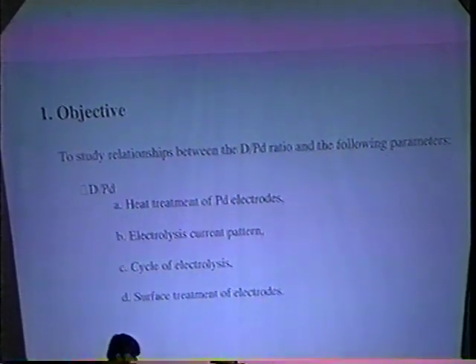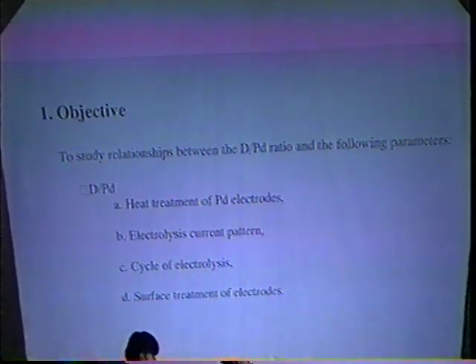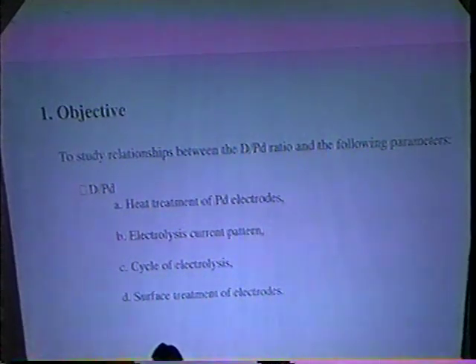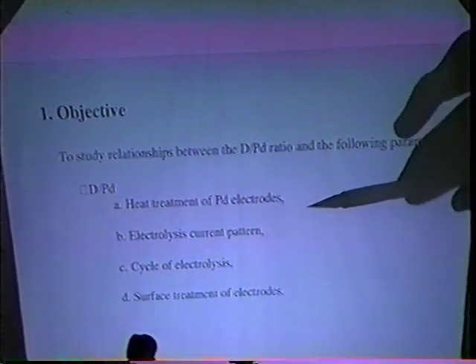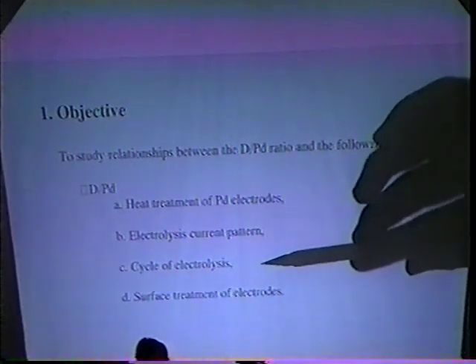The ratio was studied using a resistance measurement method in order to establish a procedure for accepting electrodes which can be expected to give a high ratio. In this study, relationships were found between the ratio and the following parameters. Heat treatment of palladium electrodes. Electrolysis and current pattern. Cycle of electrolysis. Surface treatment of electrodes.